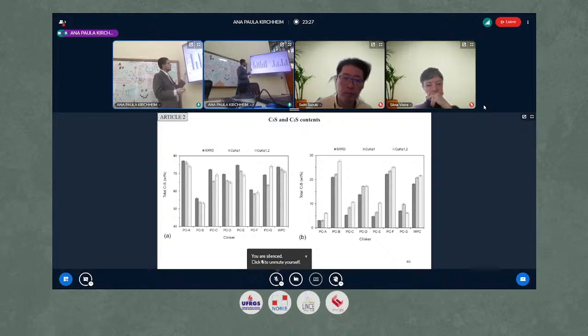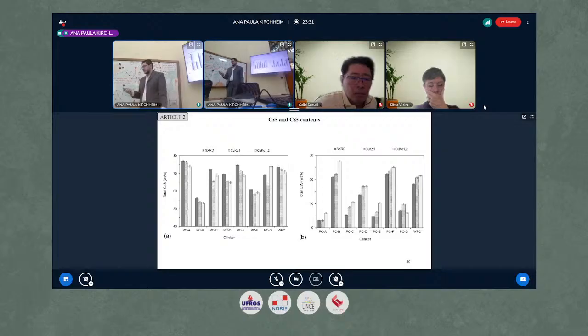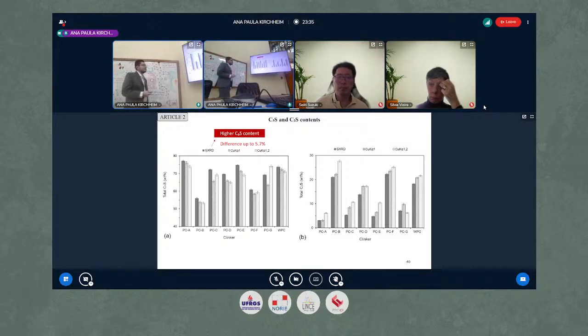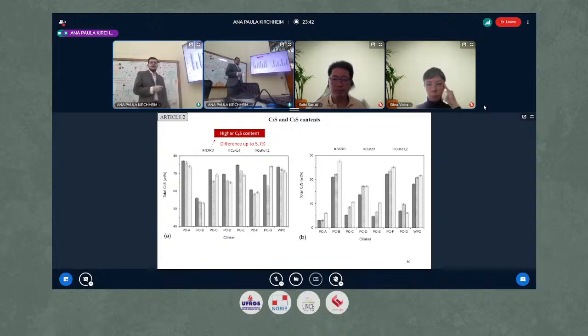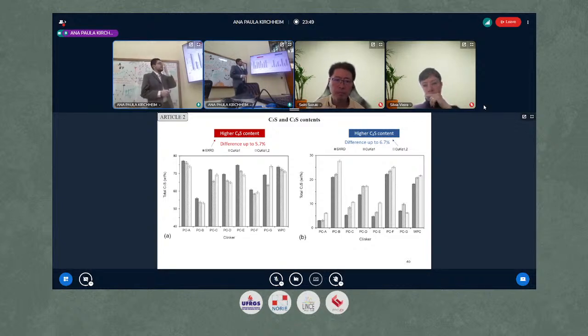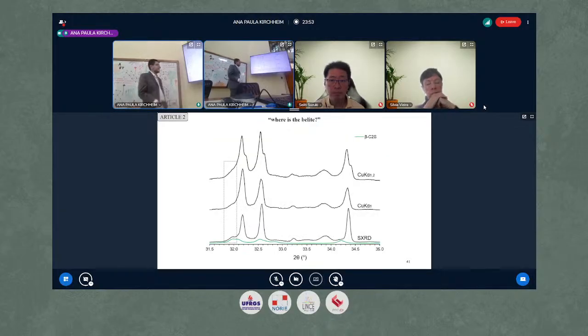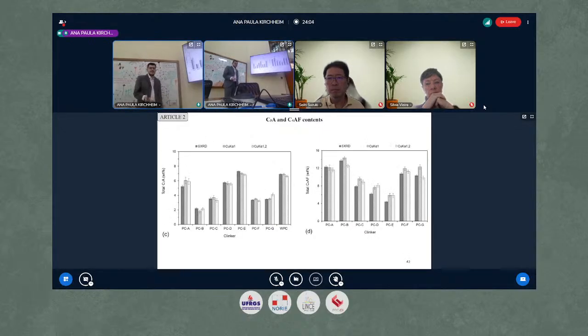So here we see a significant influence of the XRD setup on the alite and belite quantity. The synchrotron XRD led to higher C3S content, with differences up to 5.7%, so very significant, while the lab XRD without monochromator led to higher belite content, with differences up to 6.7%. And this graphic here may explain why there is a great effect of the XRD source on the belite and alite composition. In terms of the aluminates C3A and C4AF, the influence was not significant. All presented similar quantities among all the setups used.